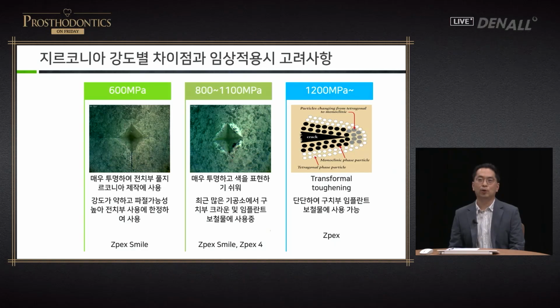There are things to consider in terms of strength and clinical application. In the past, we used a 3 mole yttria zirconia. It had very high strength of 1200 to 1300 megapascal. This is because of transformal toughening. The mechanism that inhibits cracks only exists in 1200 to 1300 megapascal zirconia. It's very hard. It can be used for posterior implant prosthesis or custom zirconia abutment. You can use 3 mol yttria zirconia with 1200 or 1300 megapascal.